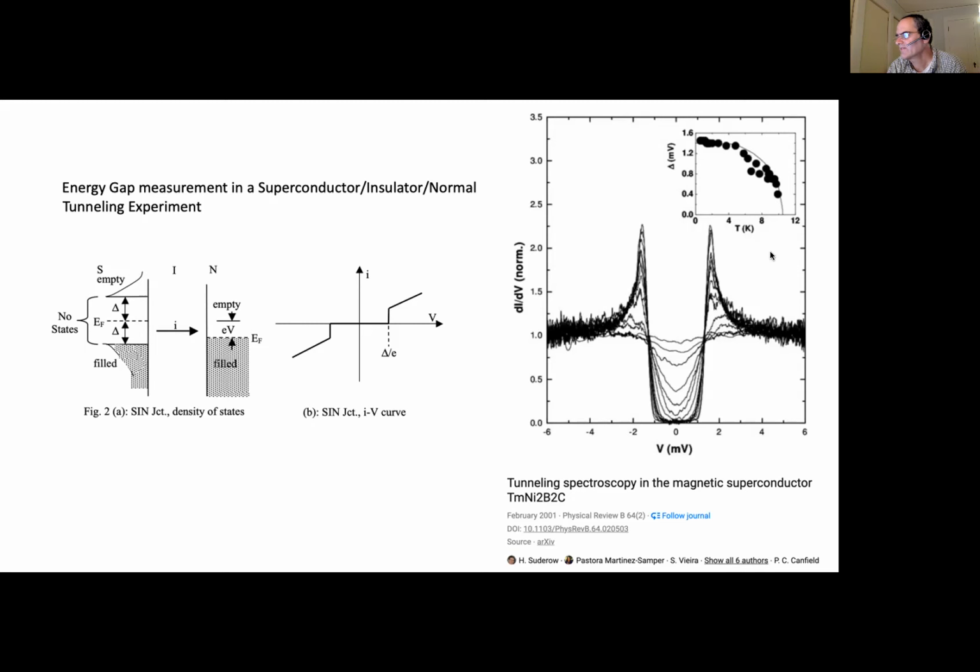Here's some data that shows the same phenomenon. Note here, they're plotting the slope, dI/dV, as a function of voltage. So you can imagine the slope here should be positive, and then it should get very large, and then it should go to 0. Then it should get large again, and be a positive finite number after that. And that's what we see. We have a positive slope for negative voltages, then the slope increases, then it falls to 0 when we're within the gap, then it goes back up and goes back to a constant value.